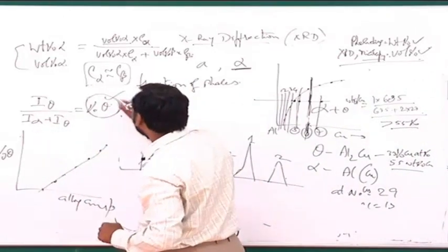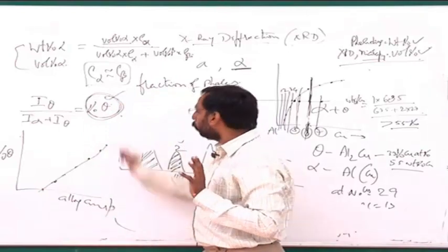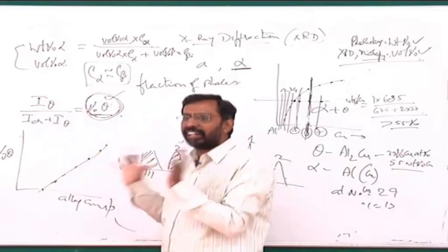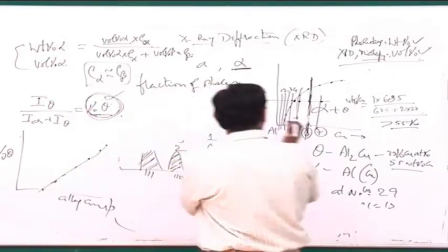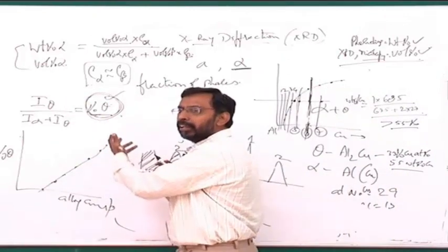Simply I take the ratios and plot this ratio. Consider the ratio to be giving some number, which I will call a fraction of the phase. Though I know that this fraction of the phase I am calculating from this ratio is not exactly the correct value, it is the same for 5 and 6 and 7. The error whatever I am doing will be similar in all of the cases. So simply I plot that and find out where it is going to 0.